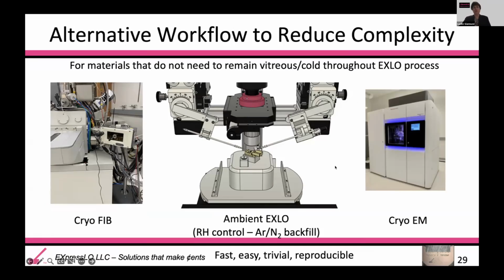So just very quickly, we also have alternative workflows for specimens that do not need to remain cold or vitreous through the ex situ lift out process. This is extremely easy. We don't have to do in situ lift out cold. So we can do all the cryo FIB milling in any cryo FIB. We can do the cryo TEM. All we have to do is warm up the sample and do now ambient ex situ lift out, and this